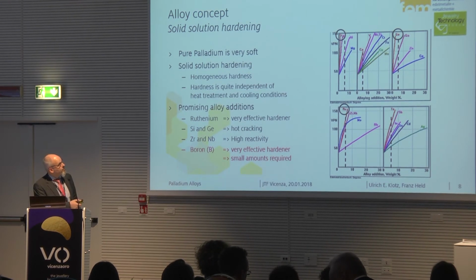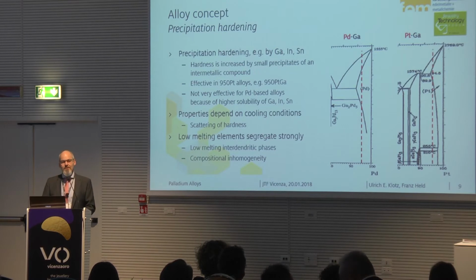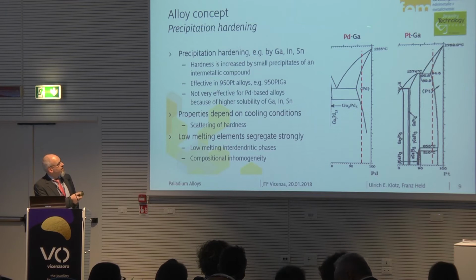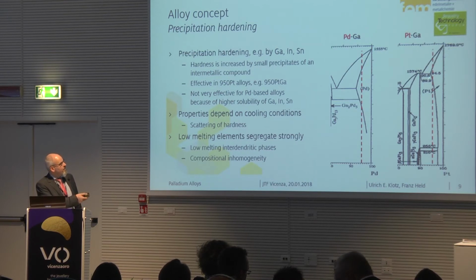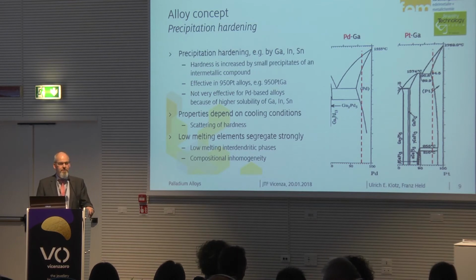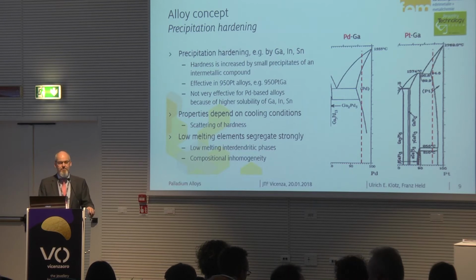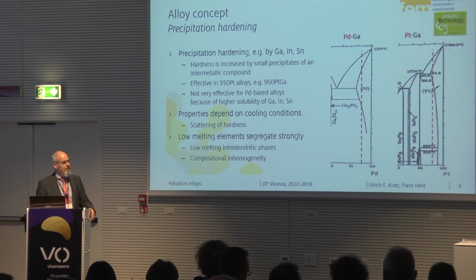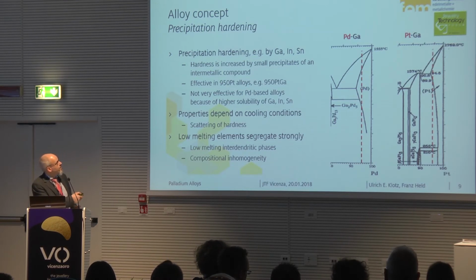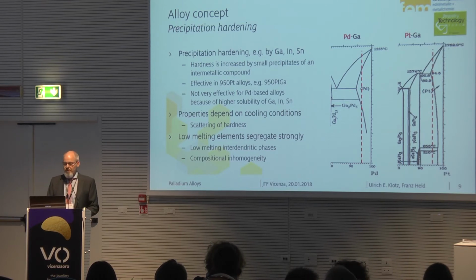Gallium is also an element that is used in platinum, but it's not working as well in palladium. So here I showed you the phase diagrams of the palladium-gallium and the platinum-gallium system. The red line shows 95%. And here on the right side, you see the platinum system. You see that the red line is intersecting this line here, and this means there is so-called precipitation hardening. Small precipitates of an intermetallic compound of gallium and platinum form, which results in significant hardening. But this does not work that well in palladium because palladium has a higher solubility. So the hardening effect is much less pronounced, and we have similar effects with other elements like indium and tin that are other candidates. Therefore, we were not sure if gallium would be the right choice.